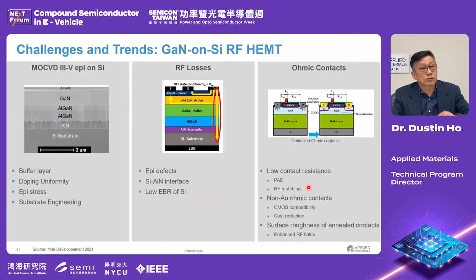And right now, for cost reasons, most of the process will be GaN on silicon for low voltage. Because of the mismatch of GaN on silicon, the buffer layer is very critical, and the doping uniformity and the stress are very important. So that's why there are different kinds of substrate engineering available. And for the RF application, the RF parasitic leak will be very critical. So the epi defect and the interface for silicon and aluminum nitride are very important.